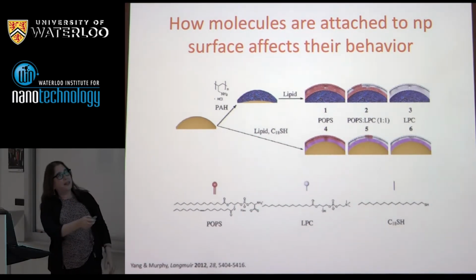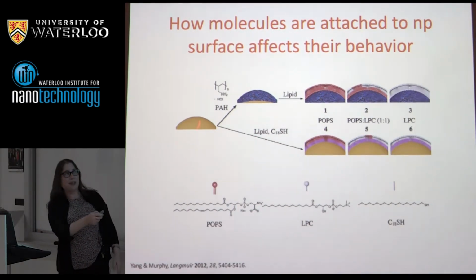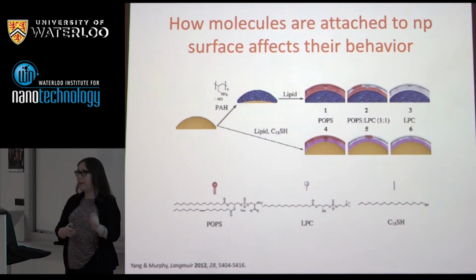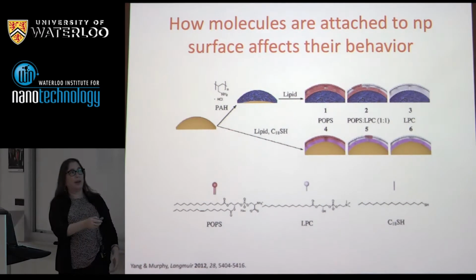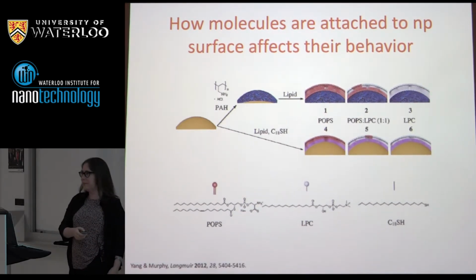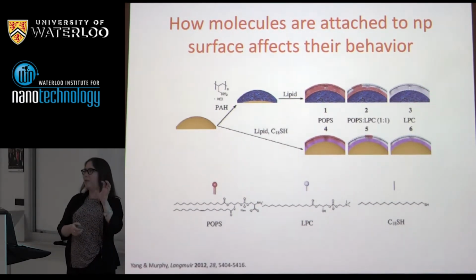Okay, so here's the idea. I'm just going to use spheres here. So I've got my gold spheres. I will go ahead and again, I will choose two different ways to attach my lipids. I'll use electrostatics or hydrophobic van der Waals interactions. So I can come in with my cationic polymer. Now I got a positively charged surface, and I can come in with this lipid or that lipid. Okay, one lipid, another lipid, or the interesting thing, a mixture of the two lipids. And then I've got a little lipid-coated particle.